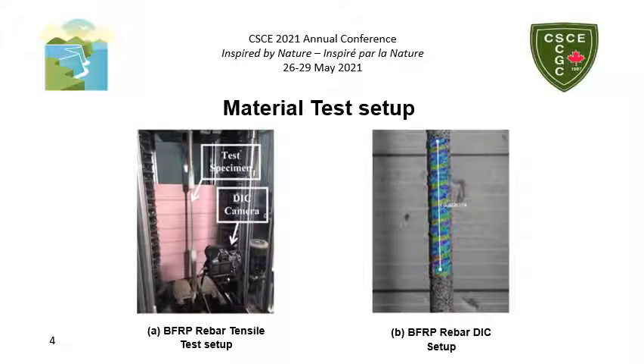The strength of the rebars was tested through direct tensile tests in accordance with ASTM D7205. The test setup is shown in these two figures. The digital image correlation technique, or DIC, was used to extract the strain data. This technique consists of taking pictures of the speckle pattern applied on the surface of the specimen and then comparing the pictures frame by frame with computer software.